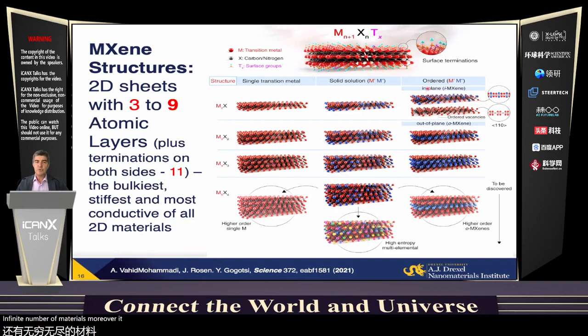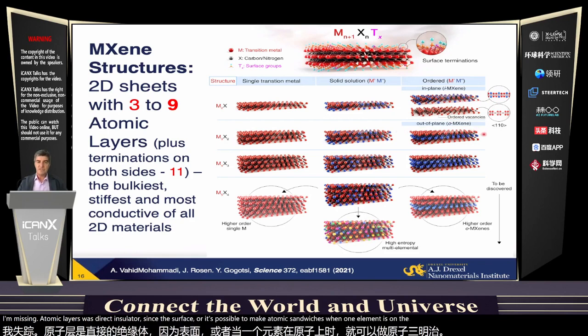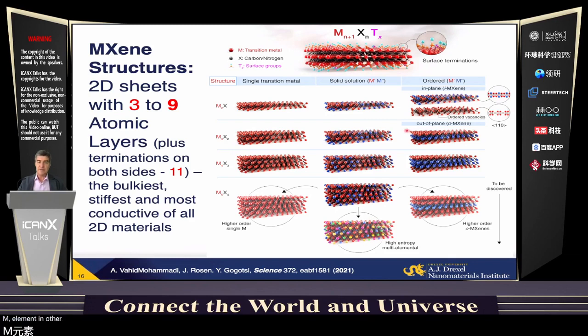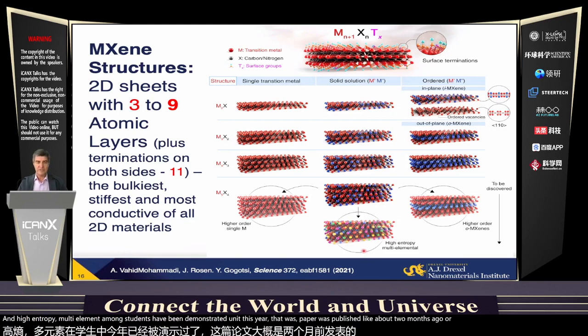Moreover, it's possible to order the M element in plane. So we have in-plane ordered i-MXenes, where one can make an atomic column of one M element, for example, scandium or yttrium, leaving molybdenum or tungsten on the surface, and get materials with missing atomic layers, with divacancy layers on the surface. Or it's possible to make atomic sandwiches when one M element is on the surface and another is in the middle layer, for example, molybdenum on the surface, titanium in the middle. And high entropy multi-elemental MXenes have been demonstrated earlier this year. The first paper was published about 2 months ago or even less.